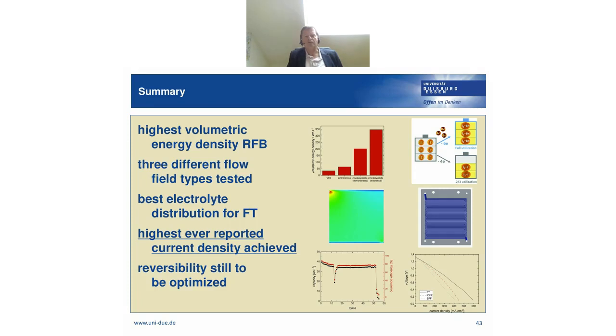But of course, the reversibility, and we think especially on the zinc side, has to be optimized. So this is really the point where we do a lot of experiments right now. And of course, a little bit larger stack is under construction. We build a stack based on an active area with 250 square centimeter, and we will show a 5 or 10 cell stack of this size.